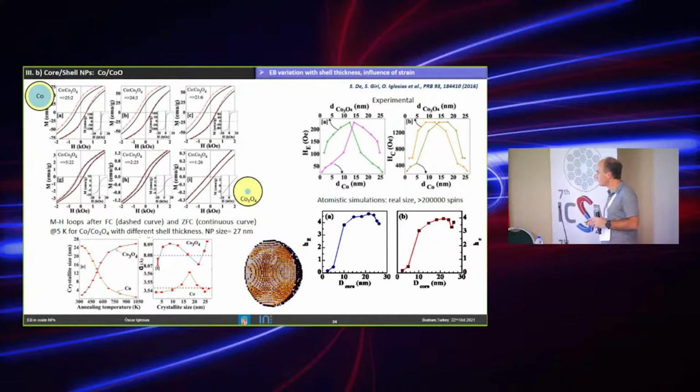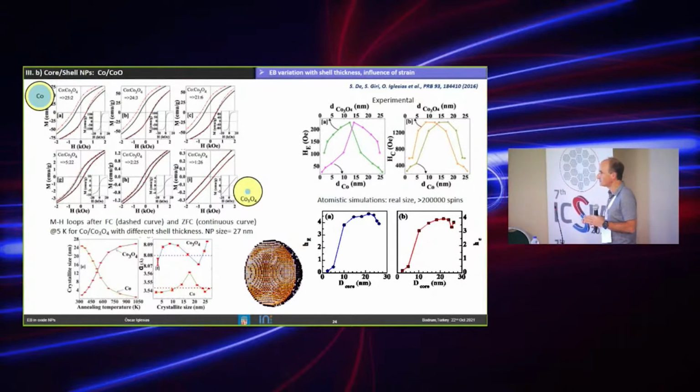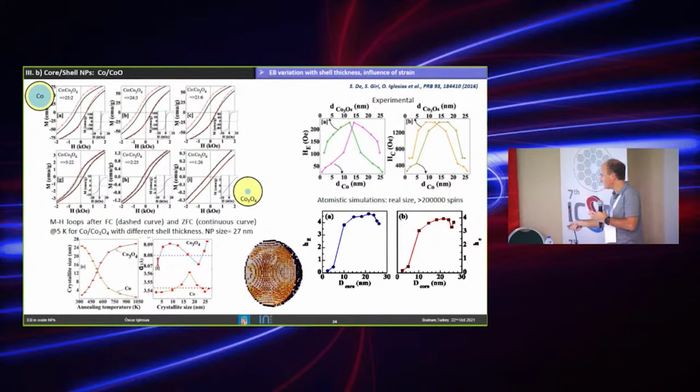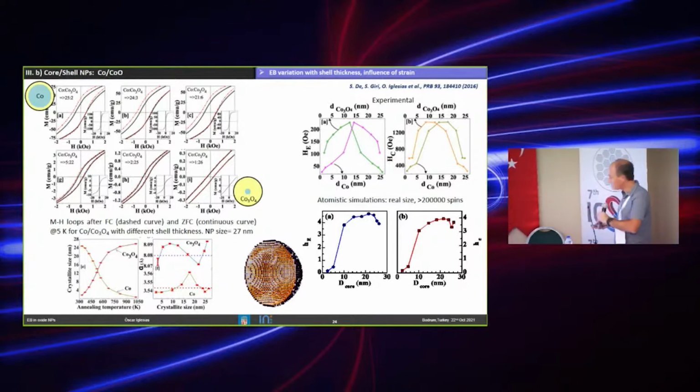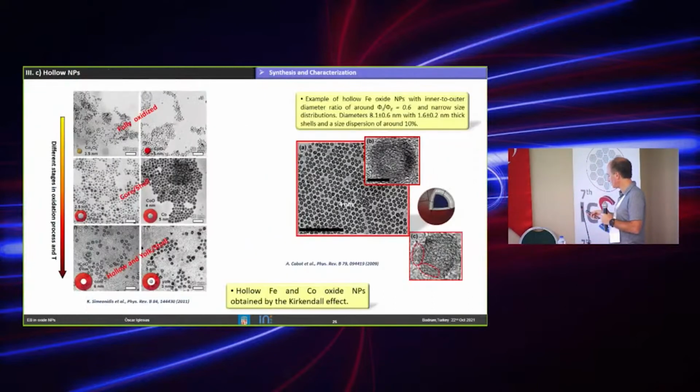You can even match which spins, the lighter ones here, do not reverse at the interface exactly, right? And you can see that the ones on the inside reverse more than the ones in touch with the shell, which are the ones in black here, right? So again, the atomistic level matters in order to understand all this phenomenology.